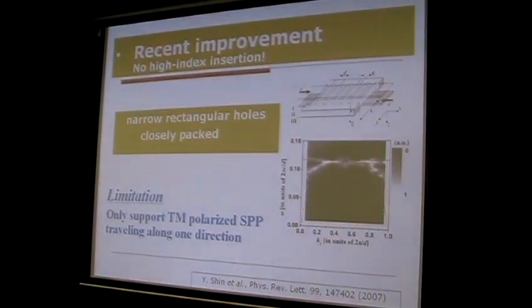Also in that structure, you use a fractal structure. The purpose of using this fractal structure is that the plasmonic structure can be multi-band. But multi-band is only one advantage. I think the most important thing is that a fractal structure can be very sub-wavelength. For the lower resonance mode, it can be very sub-wavelength. I have shown you in the previous work that this very small structure can support a very long wavelength. That is a very unique property of the fractal structure. If you use a single structure, it can only support a half-lambda resonance. So that's why we use the fractal structure. The sub-wavelength structure is the most important consideration.